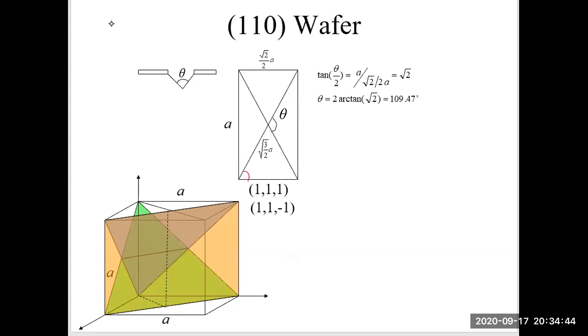So this angle is equal to theta over 2. The tangent of theta over 2 is equal to this distance a divided by this distance, square root of 2 over 2 times a. So tangent theta over 2 is equal to square root of 2, and theta is equal to 2 times arctangent of square root of 2, which is 109.47 degrees. So this angle is different from the angle in a 100 wafer.